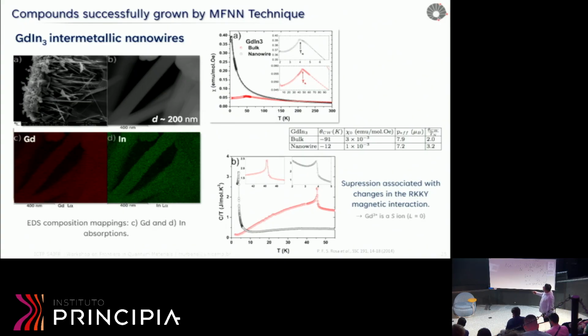Here we have single crystals on top of the template and inside of the nanopores, and when this was removed from the template, we got these nanowires here. And again, this was a very interesting result because, well, first we can check the phase purity of these materials, gadolinium indium. But what is interesting to us is this: T_N was suppressed from 45 Kelvin down to 3.8, just by having this new morphology of materials here.